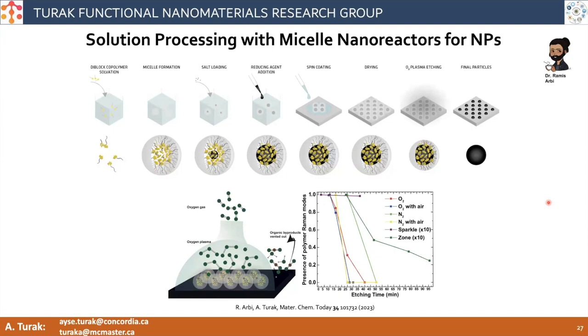And we've explored a number of ways of doing that. Different plasmas have different effects. Oxygen plasma is obviously quite useful if you want to make metal oxides, for example, because the oxygen is a primary component of forming that oxide. But you can also swap it for other techniques with different levels of success, depending on what you want. It is, in fact, possible to use an ozone-type technique to just clean the polystyrene portion and leave the hydrophilic portion inside. These kinds of things can be beneficial if you want to have a decorated or functionalized structure.